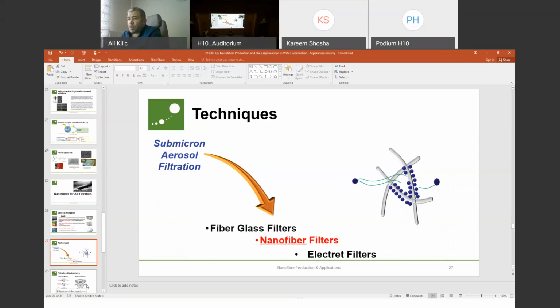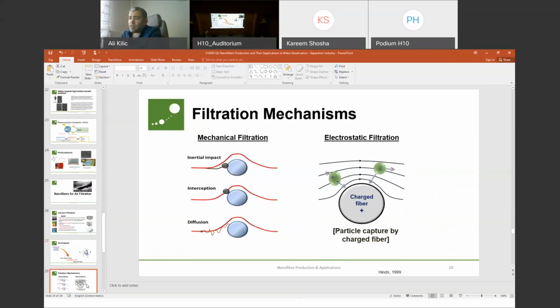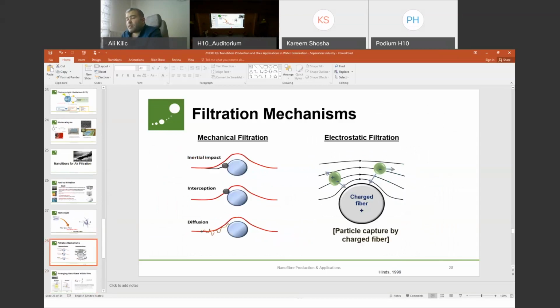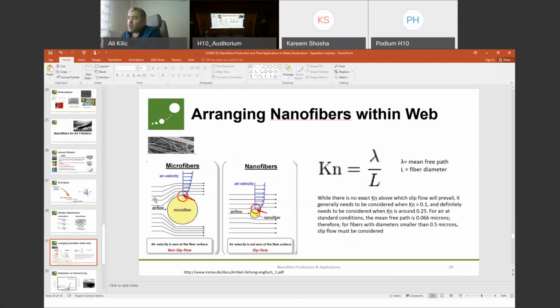This is kind of different compared to membrane separation techniques. Air filtration is not a similar separation technique. For air filtration, we can capture particles from different distances, and there are mechanical filtration and electrostatic filtration mechanisms. So we follow these mechanisms. If we reduce the porosity of the samples, again, we are able to enhance the filtration performance. Another important gain when we use nanofibers is the flow again. If I sum up, the nanofibers are basically increasing the flux or flow rate, even for air or water.